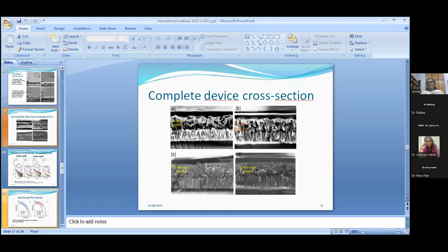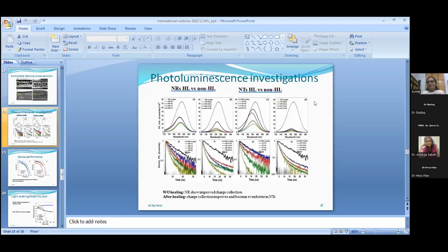Now we have the PL investigation of nanorods and nanotubes with healing and without healing. These are also thickness dependent, nanorods and nanotubes with healing and without healing. And these are the nanorods and these are the nanotubes. One can see that the intensity is slightly reduced in the nanorods after healing due to the quenching effect, meaning we have greater charge extraction. But this trend is more clearly seen in the nanotubes after healing. After healing, there is a clear reduction of the intensity in the nanotubes due to the quenching effect, meaning we have greater charge extraction at the selective contacts after the healing.